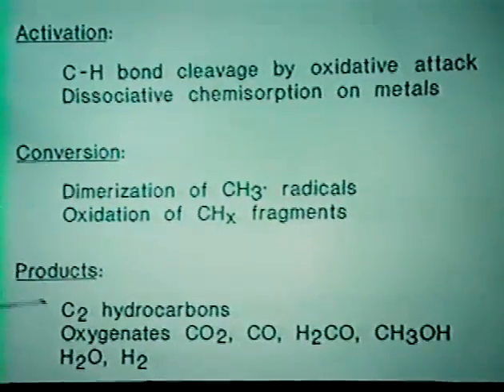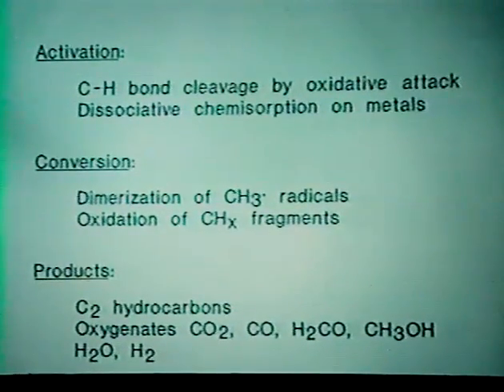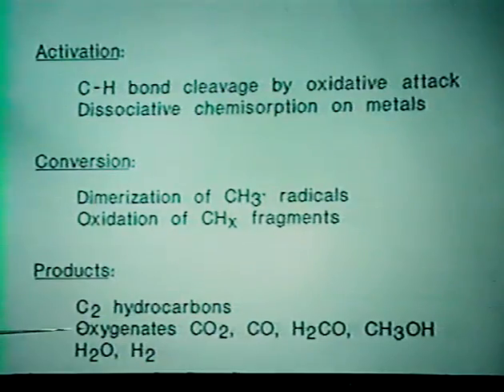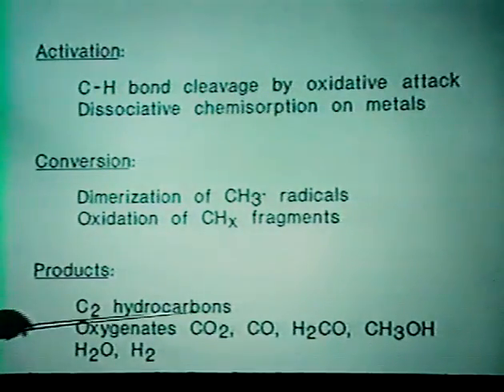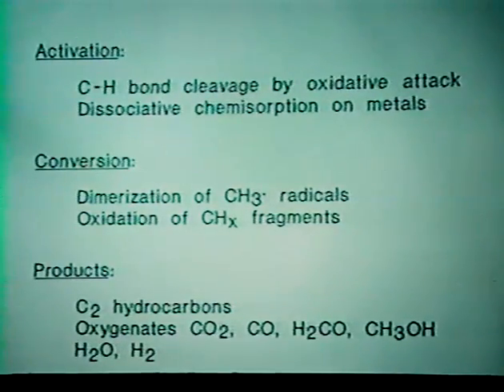The products that are made are C2 hydrocarbons, ethane and ethylene, and of course you can burn methane to carbon dioxide. If you burn methane to carbon monoxide, it's not all that bad if the co-product of that reaction is hydrogen. And you can burn methane under certain conditions partially to formaldehyde, and what was denoted to be one of the greatest challenges by catalytic associates was to selectively oxidize methane to methanol. And the products obtained from hydrogen oxidation of methane are water or hydrogen itself.